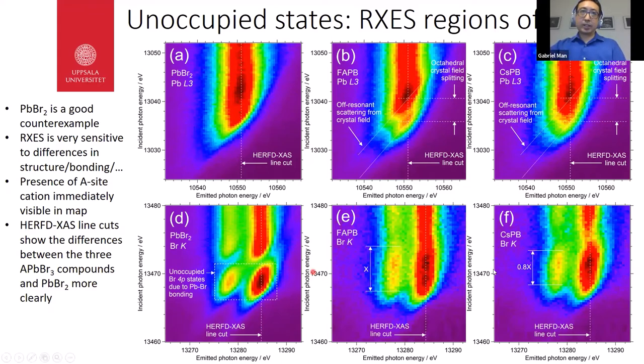The lower row here shows all bromine K-beta regions of interest. For lead bromide, when we compare figure D to figures E and F, we immediately see that once we have the A-site cation in place, the spectra look very different. So we can already guess that the higher energy portion of the main edge could be related to the A-site cation.